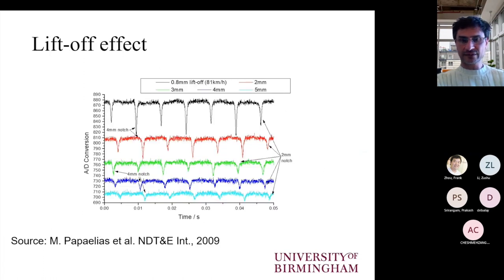And here is another set of measurements at the constant speed of 81 kilometers an hour, but different liftoffs. So you can see at 0.8 millimeters, 2, 3, 4, and 5 millimeters, in all cases, the defects are successfully detected, even though the signal, as you can see, drops as we increase the liftoff. But they are still detectable, and these are very small defects, as you can see.